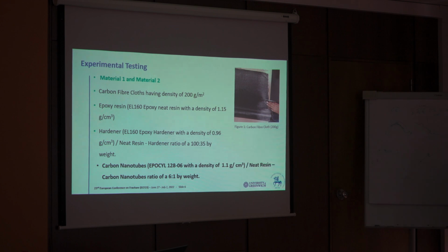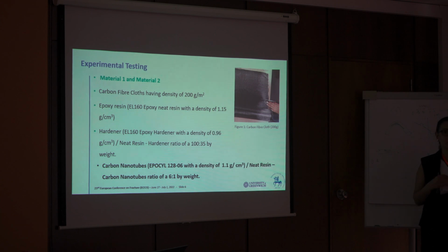But after some experiments, unfortunately we saw that the hand layup technique is not quite effective for this type of material. So then we switched to the vacuum infusion technique, which allowed us more homogeneous results for the composite materials. Although for the hand layup technique we were able to get some results, the standard deviation was not quite satisfying.